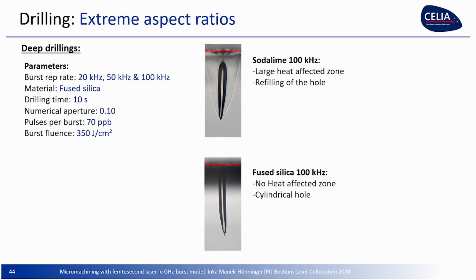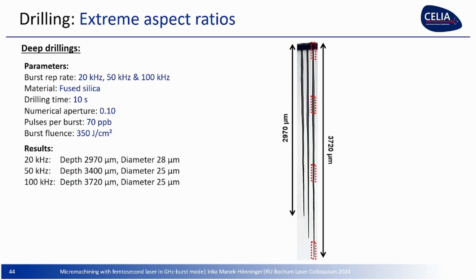First, we take the material, we take fused silica and not soda lime, because when we want to increase the rep rate, you saw we can increase the depth. But soda lime is subject to heat affected zone. The hole collapses. It's even closing here. It's refilling. So we take fused silica, and as you can see, we can go very deep. At 100 kilohertz, we went down, the diameter measured here is between 25 and 30 maybe microns, but we went down to almost 4 millimeters, without moving the sample and without moving the laser beam, the focus.